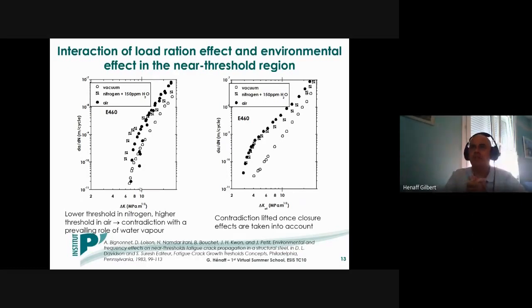Another example of possible interactions is the effect of the load ratio, especially near threshold. So here, in the case of a structural steel, on the left-hand side, we compare fatigue crack growth rates obtained in vacuum and in air, just like in the previous example, but also in an atmosphere constituted of nitrogen with some traces of moisture, namely 150 ppm of moisture. And what is surprising in that case is that the threshold value seems higher in air, or comparable to vacuum, and the lowest threshold value is obtained in this intermediate atmosphere containing only traces of water vapor.